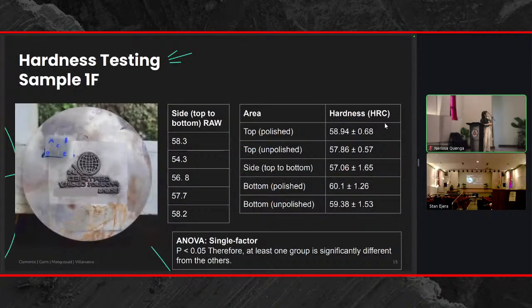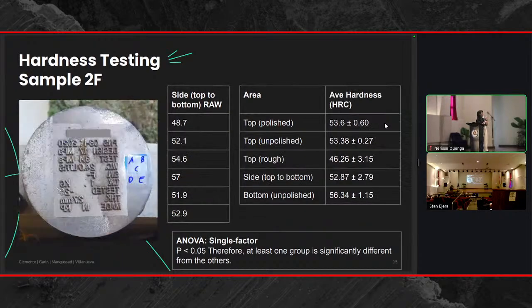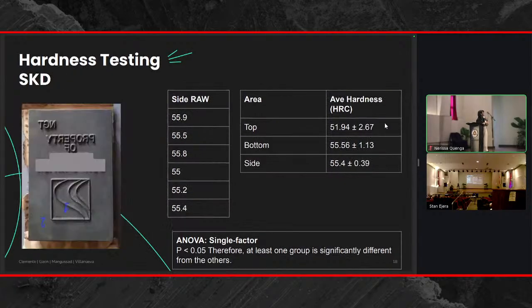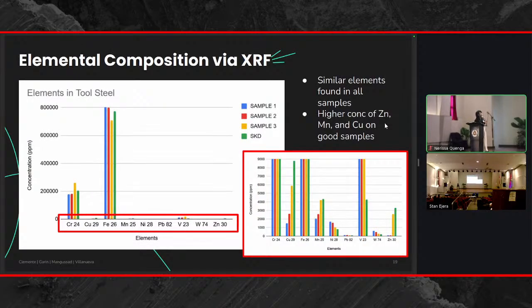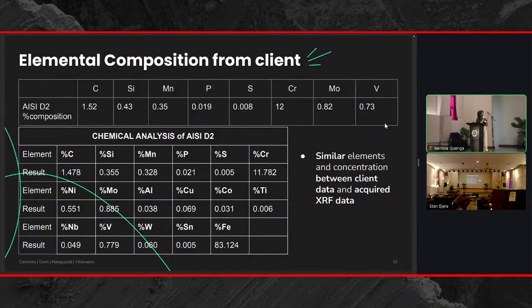For results of NDT, a significant hardness gradient was found for both sample 1F and 2F, while it was relatively consistent in sample 3NF. The expected elemental composition for AISI D2 was also found in all samples, though it should be noted that there was a higher concentration of zinc, manganese, and copper found in the good samples. Here in the inset bar graph, we can see that samples 1 and 2, the red and blue graphs here, have notably lower counts of these alloying elements, and the SKD sample also had a remarkably lower count of vanadium. This was also similar to what we received from the client.